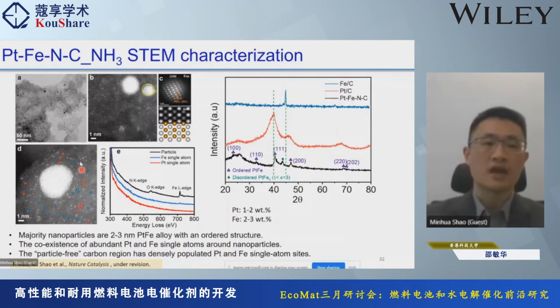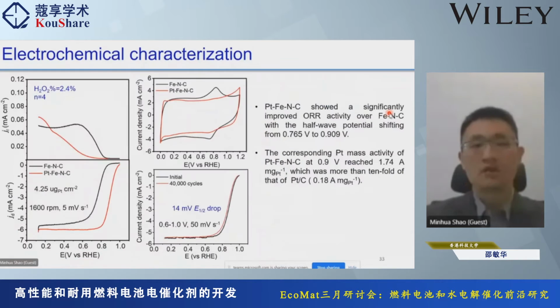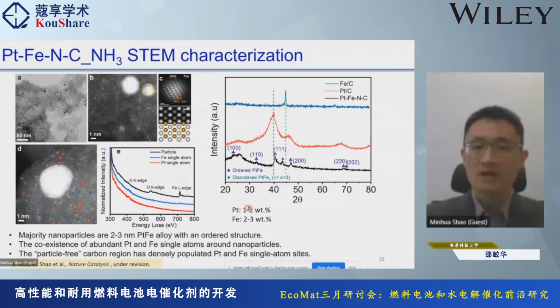Okay, so you have different types of single atoms combined with small nanoparticles. This is further characterized by X-ray diffraction, showing this ordered platinum iron structure. We also did some electrochemical characterization. You can see that in the RDE, the activity of the platinum iron nitrogen has about a 150 millivolt shift. Okay, so that's significant. And the loading of platinum is only 1 to 2 weight percent, and iron is about 2 to 3 weight percent, very low metal loading.